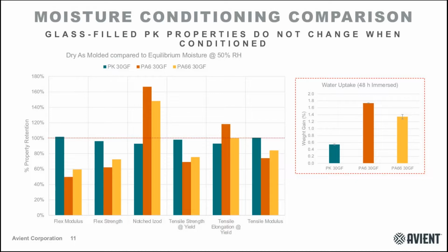And this moisture uptake is important for how it changes the physical properties. What we're going to be talking about on this slide is the property retention of polyketone compared to nylon 6 and 6/6 when you're looking at samples that are dry as molded versus conditioned. This can be important because you might look at a technical data sheet and see properties for a nylon or nylon 6/6, and it's one thing to see a property when it's dry as molded, but when you understand that moisture is going to affect those properties, you want to understand how it's going to affect your ultimate part performance. So it'd be good if you only had to measure those properties once, or you could trust that your dry as molded data is going to be indicative of your performance.